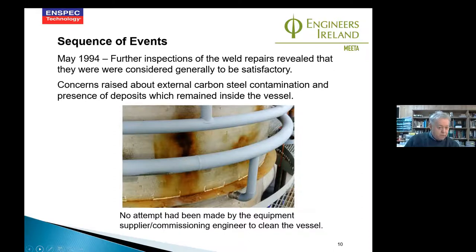When I saw this, I understood why it was there — the deposits were caused by overspray when the gray carbon steel pipe sections were being welded. Those two circular rings are the steam inlet rings, and when the pipe was cut to fit, ground, and welded, the overspray naturally started to rust in the humid marine environment. As time progressed, this needed to be rectified as well, and indeed it was. This was in May 1994, and the plant was being built with commissioning planned for the summer of 1994.